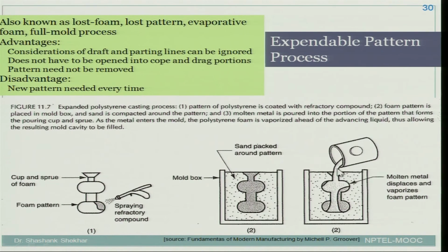Why? Because this polystyrene foam can very easily melt and escape. So when we pour the liquid metal, the polystyrene foam will melt and escape from here and create the hollow space that is needed to fill the liquid metal, and therefore this process is called the expendable pattern process.